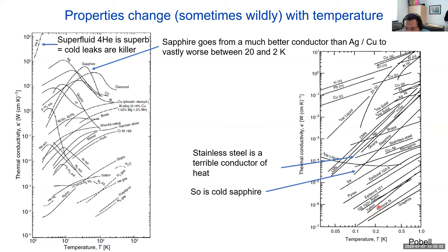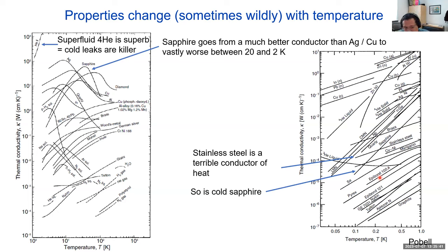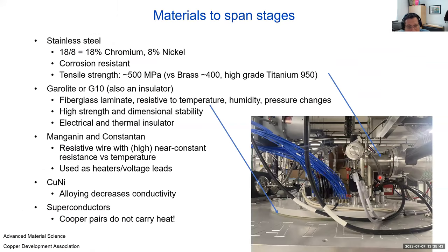Just a few other fun things: here's nylon, Teflon, graphite. Apiezon is a cryogenic grease. The takeaway is to not trust anything at 4 Kelvin to be true at 10 millikelvin. In my mind, there are kind of different sets of materials and what they do. Aluminum is a mediocre conductor at room temperature, pretty okay at 4 Kelvin, and superconducting below one Kelvin. Every material sort of has to be classified differently in your mind at the different stages of the dilution fridge.